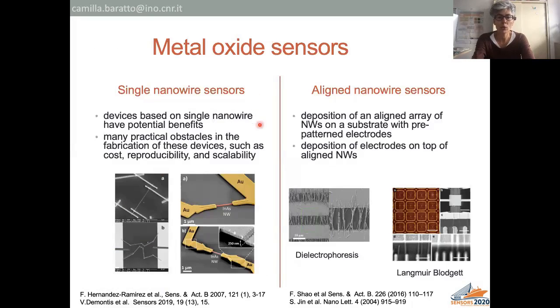So single nanowire sensors are very nice to describe the working of the material, but unfortunately the problem is to make reliable contacts, and one has to use electron beam lithography or focused ion beam to deposit contacts over a selected nanowire.